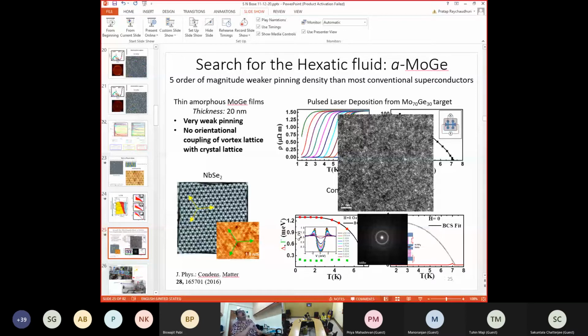Therefore, after quite a bit of search, we decided that a good candidate for us would be amorphous molybdenum germanium. Molybdenum germanium is often written as MoGe, which doesn't mean that it is 50-50. The composition is more like Mo70Ge30. We made these targets in Thamizhavel's lab again, and with pulsed laser deposition we could make these amorphous MoGe superconducting films which have a Tc of something like 7 Kelvin.